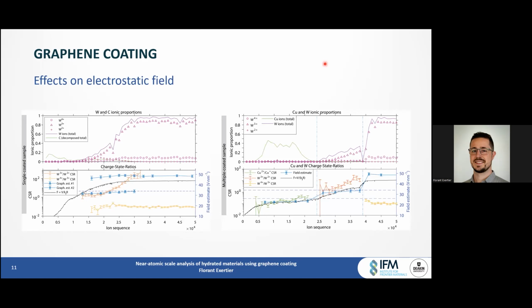The electrostatic field was estimated for the single coated layer specimen and the multiple coating layer specimen using the charge state ratios of tungsten and of copper when applicable. And a lowered electrostatic field was measured for the sample with several coating layers compared to the single coating layer, which is in line with our initial hypothesis.